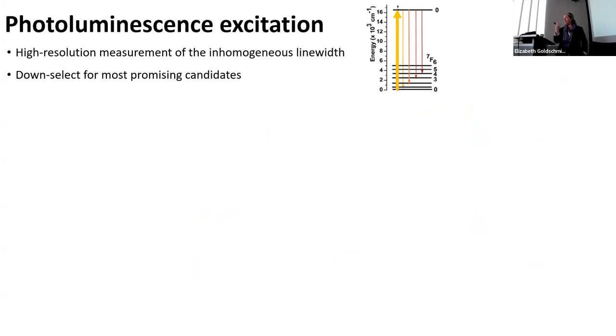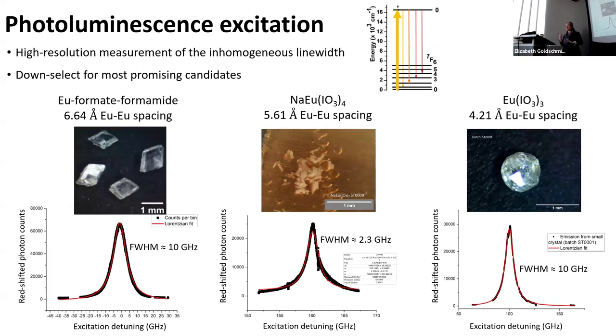So here we have a narrow band tunable laser. We tune it across the transition of interest, and we just look at how much light comes out as a function of the excitation frequency. So we use this to down select. In work that will be written up soon, we've found three decent candidates to start with.